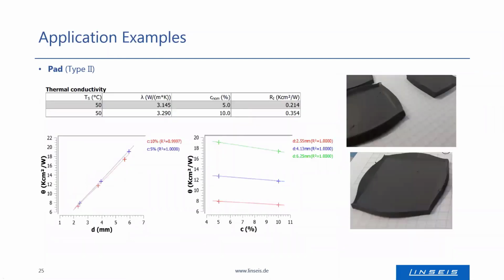In this example, you can see a pad, which belongs to the type 2 thermal interface material. Here, the sample temperature was set to 50 degrees Celsius, and for each sample thickness, a compression of 5 and 10% were defined. So the sample thicknesses were 2.5, about 4, and roughly 6 millimeters.